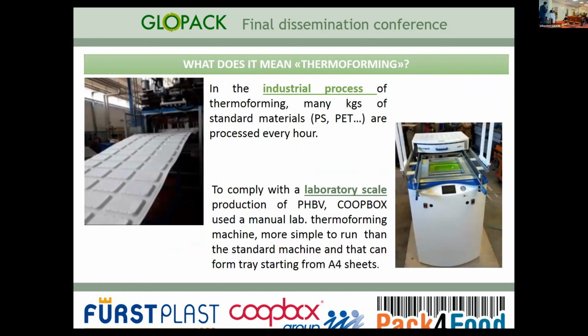In the industrial process, usually there are different steps. The first one is the extrusion of foil, like Cornelia explained before. The extrusion at the industrial scale is usually made on machines that are able to produce typically 1 ton of material per hour, so with a very high output. These rolls, typically of PET, PS, or PP material, are then processed on thermoform machines that are able to consume 100 kilograms of material per hour, and the output is around 10 or 20,000 trays per hour. So you have to consider that it's quite a high quantity, but it's the industrial part.